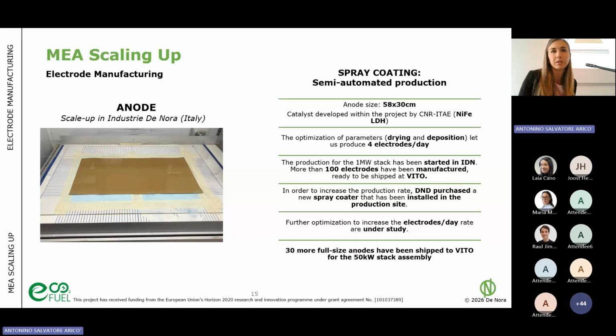Here are some images of the electrode that we can make. It is 58 by 30 centimeters. We are depositing, in this case, the nickel iron LDH catalyst developed by CNR. And as I said before, in this case it is a semi-automated production, because the optimization of the parameters lets us produce 4 electrodes per day. So that's, let's say, 5 if we really stretch our time, but no more.